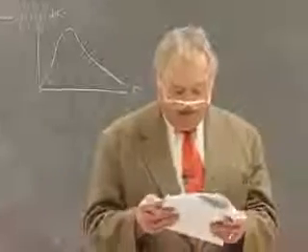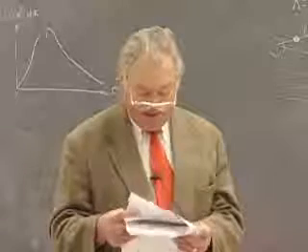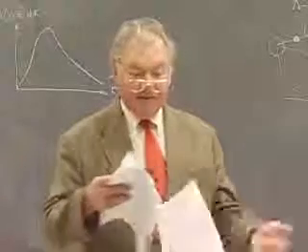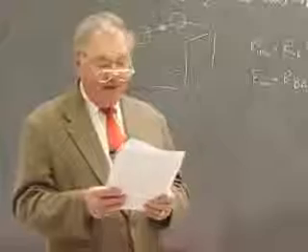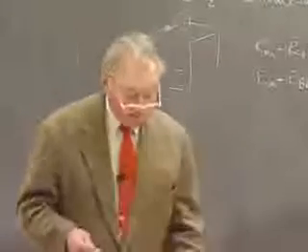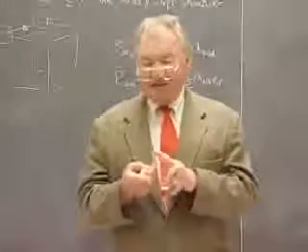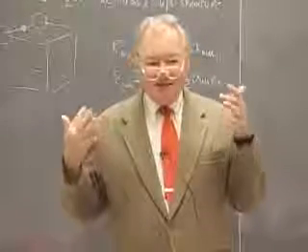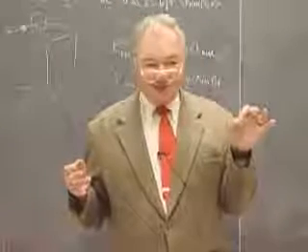All right. Where do you get polarizabilities from? This was looked at by a number of people. One of the most complete were 3 people, Tessman, Kahn, and Wild Bill Shockley of transistor fame. So you can find these numbers and you can get a self-consistent set of radii. But note in the table that I give you here that the individual numbers are very different. And 2 caveats that I have to issue is you can't mix ionic radii in different people's tables because they have different starting assumptions for the standard radius. If you do that, you're mixing apples and oranges.